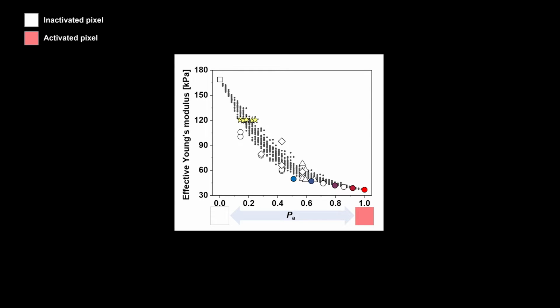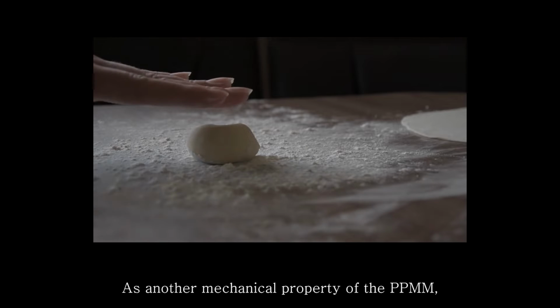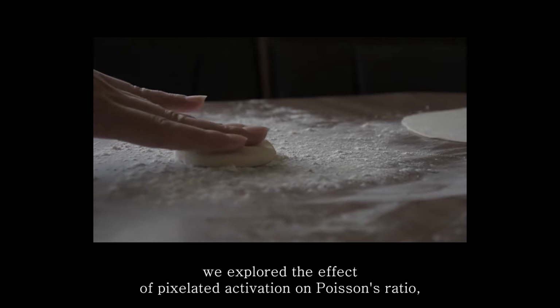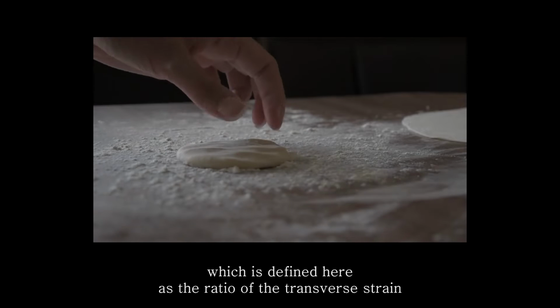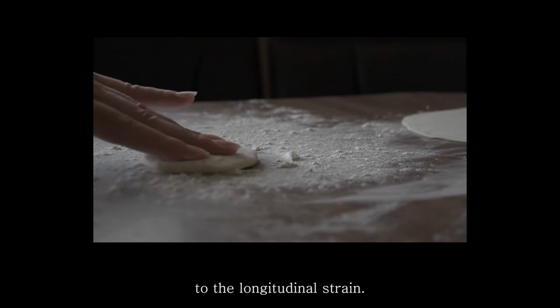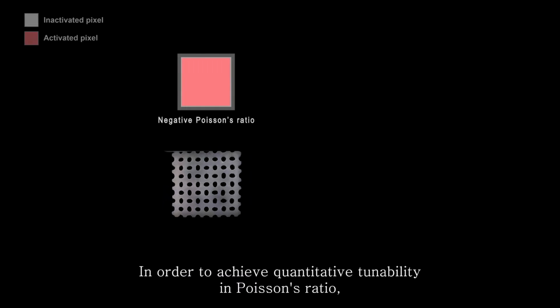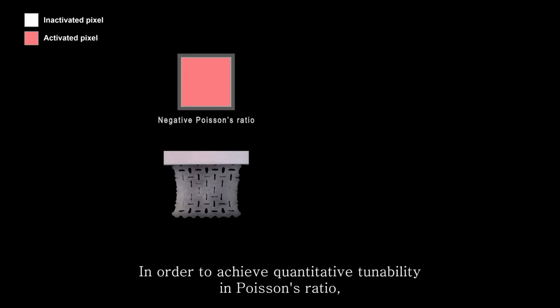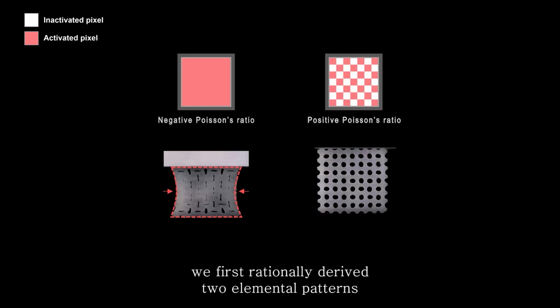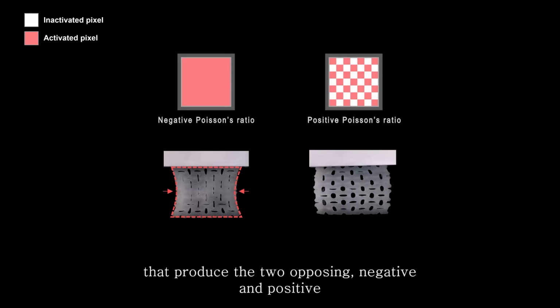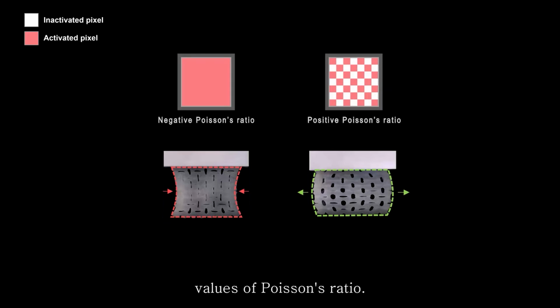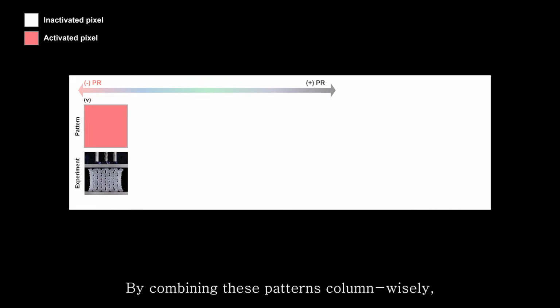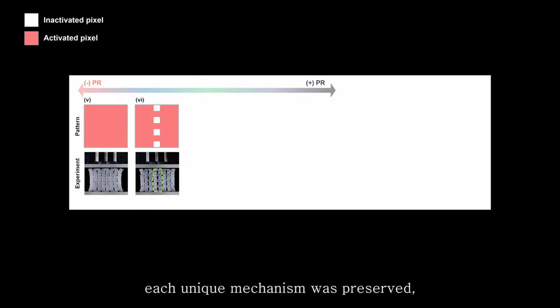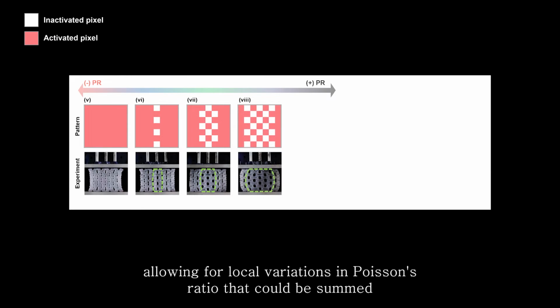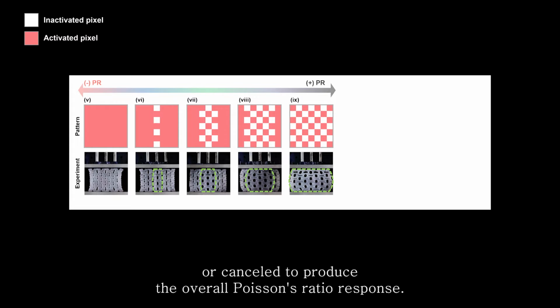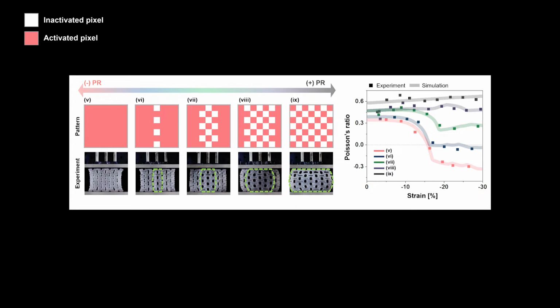As another mechanical property of the PPMM, we explored the effect of pixelated activation on Poisson's ratio, which is defined here as the ratio of the transverse strain to the longitudinal strain. In order to achieve quantitative tunability in Poisson's ratio, we first rationally derived two elemental patterns that produce the two opposing negative and positive values of Poisson's ratio. By combining these patterns column-wise, each unique mechanism was preserved, allowing for local variations in Poisson's ratio that could be summed or cancelled to produce the overall Poisson's ratio response.